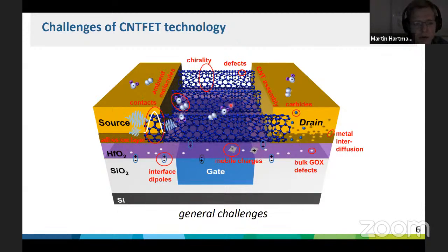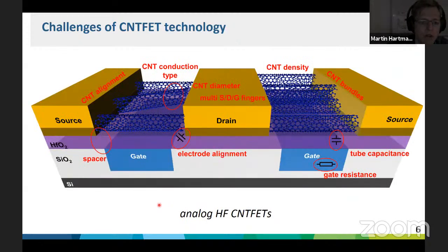And this is especially important when you think of analog CNT FETs, because these facts here are in general true for CNT FETs, whether you want to use them for analog RF applications, as sensors, or for other things. But when you look at analog high frequency CNT FETs, there are some more aspects that you need to keep in mind. Okay, one is the exact geometry and the spacer, because you have a certain capacitive coupling between the electrodes, so the drain, the gate and the source. And these are parasitic capacitances, and of course you want to reduce them to a minimum in order to have the highest operation speed of your device.